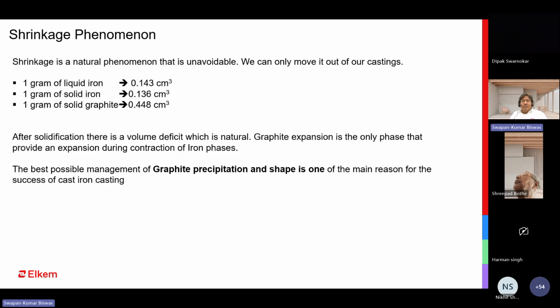During solidification, everybody knows that there will be contraction as a metal phenomenon, that it will contract, and when this graphite precipitates, it will expand. So when these two parameters are almost similar, then you will get the defect-free casting. So graphite precipitation is in our hand, but metal contraction during solidification is the metal characteristic.